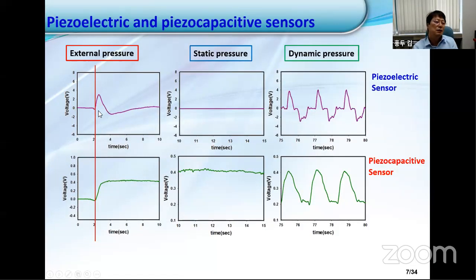case of a piezoelectric sensor, it responds very quickly. And as you see here, with dynamic pressure, it picks up the fine details of that external pressure. But if you just press down and apply a constant pressure, it does not pick up any signal. However, the piezocapacitive sensor responds to dynamic pressure somewhat slower than the piezoelectric sensor. It's because of the piezocapacitive effect. It takes some time to monitor that change.